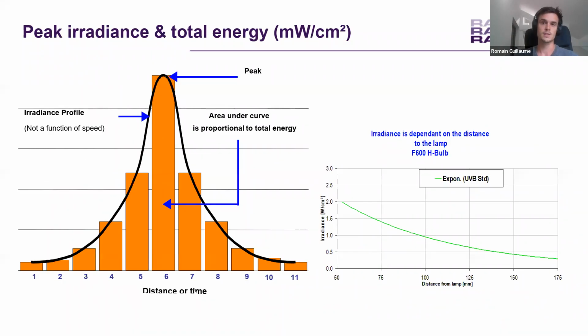Then we can jump to the peak irradiance, or the irradiance of the UV lamp, which is the instantaneous flow of photons going every second through our coating. On the left, the black curve represents the irradiance profile of one lamp. So it's the output distribution of light over your surface. And this irradiance profile also allows us to have a good idea of the total energy that could be received by the coating, thanks to the integration of it.